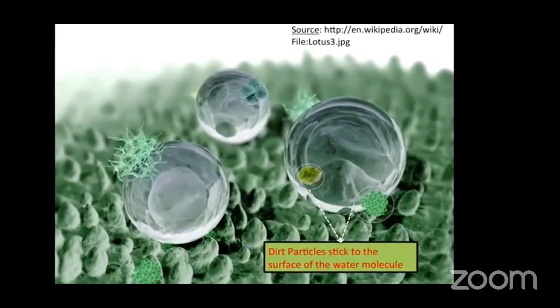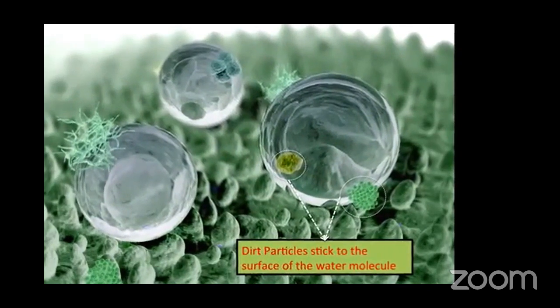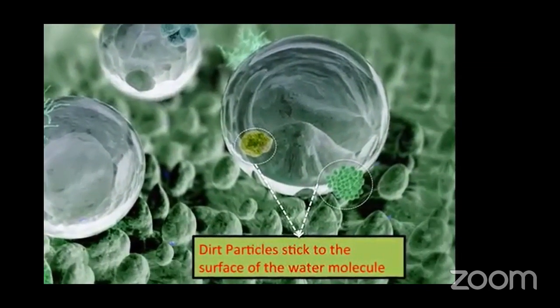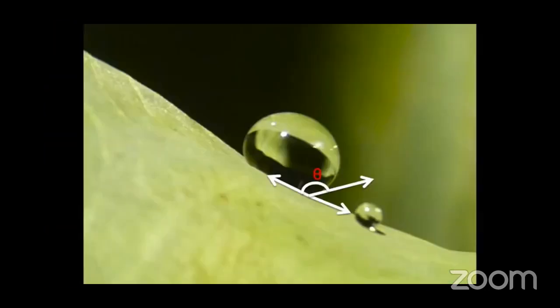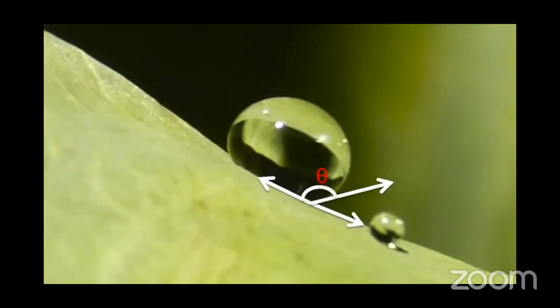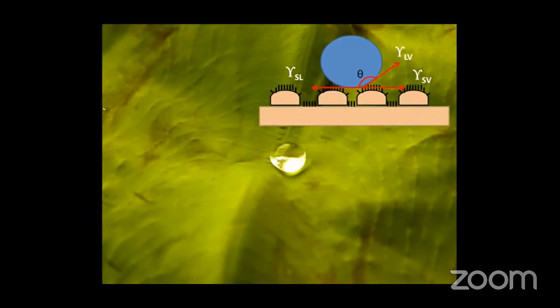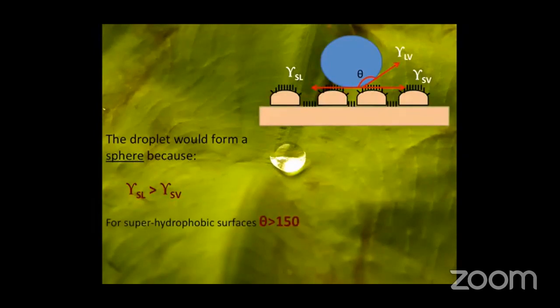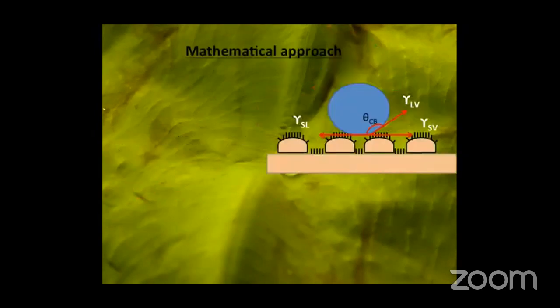This will also give the surface a self-cleaning property, in which the dirt particles tend to stick to the water molecule as it rolls off the surface. Such a surface would have a high contact angle with the liquid droplet. This is because of the low surface energy of the leaf, leading to a sphere formation of the water droplets, which minimizes the area of contact between the leaf and the water droplet and will eventually result in a high contact angle. Lotus effect can be explained mathematically by taking into account the solid fraction, air trap fraction, roughness, and the contact angle measured by Young equation on a flat surface.